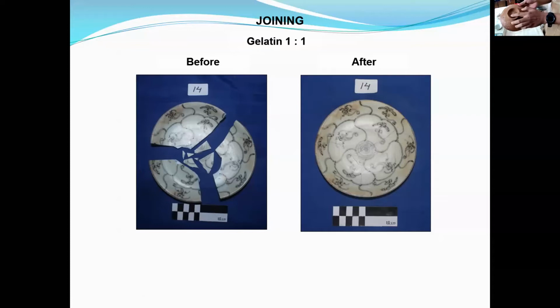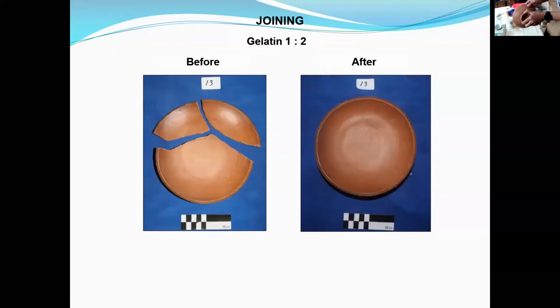The second material, this is a terracotta artifact. We joined the fragment on this one. We see that we join the fragments with gelatin dilution of 1/2. The reason that we use the less thick solution is because we expect that the less thick solution will seep into the pores of the terracotta. So it is hoped that it will be attached more strongly.